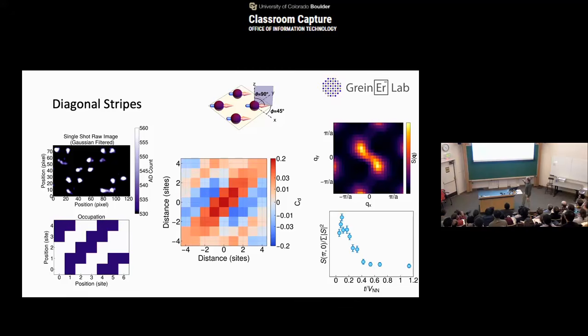One thing, what do you expect if you point the spins diagonally, right? So we tried that, and sure enough, we saw some nice diagonal stripes. Is that what you expect? It actually turns out we then did numerics, and no, numerics didn't predict that. And we did it again and again and checked the numerics, and then we realized, wait a minute.